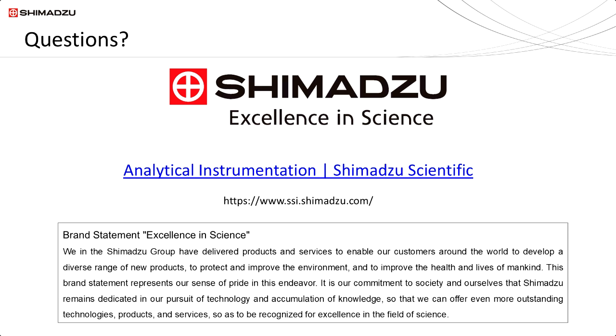And one last question about ICP. A lot of data was shown, and this question is how were the detection limits calculated? How were they determined? The ICPE solution software automatically calculates and displays the detection limit using the standard deviation of 3 replicates of blank samples and the slope of the calibration curve. We also have customers who run 7 to 10 method blank samples and then calculate the detection limit based on the standard deviation of these multiple method blank results.